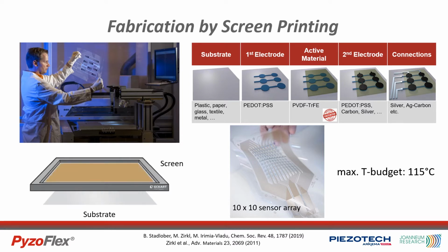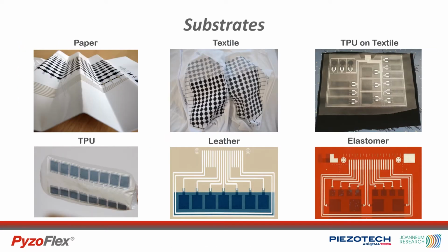The temperature budget of the printing process does not exceed 115 degrees, which is due to a special solvent based on gamma-butyrolactone. And this gamma-butyrolactone allows to induce high enough crystallinity in the ferroelectric layer already during the drying step. The low temperature budget enables the printing of sensors not just directly on polymer sheets, but also on unconventional substrates like paper, textile, TPU, leather, or elastomers. All of the sensors shown here are functional, by the way.